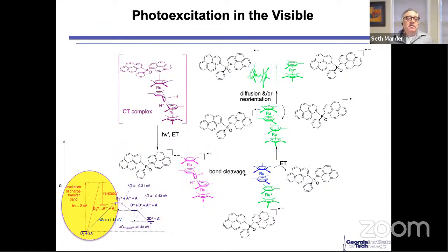Okay? And so then I recalled work from my old organometallic background of people making charge transfer complexes with metallocenes. And so I said, you know what? I bet that you're making a charge transfer complex with this metallocene, and that has an absorption in the visible. So they looked and they measured the absorption spectrum, and they could see nothing. Okay, they just couldn't see anything. I said, well, that's the only way I can imagine that this thing is working. So my speculation is you formed a CT complex in the visible, okay, that is absorbing light. And now you get that, okay, you excite into that, and then you get the charge transfer. From that point on, it's the same.